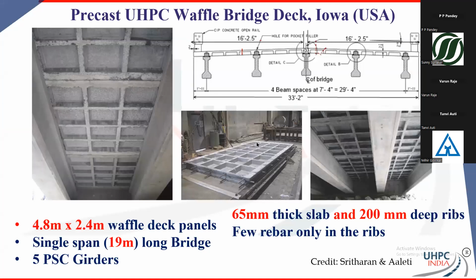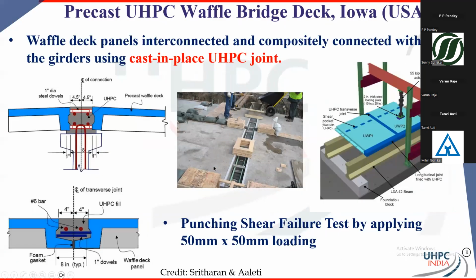Waffle decks. So these are waffle decks. This is a bridge, and you can see with a very thin waffle deck, 65 mm thick slab, 200 mm deep rib, and you can still do a deck out of it and still connect it to each other with UHPC or stitched with each other with UHPC.